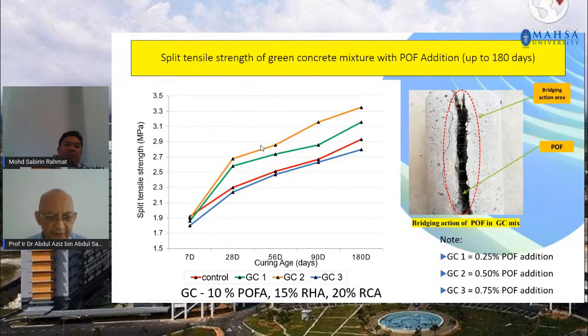Now again, this is the tensile strength of the green concrete up to 180 days. Again, the strength shows an increment of its value. As you can see, all of them show an incremental tensile strength from 28 days up to 180 days. This shows that the strength is always improving with time.